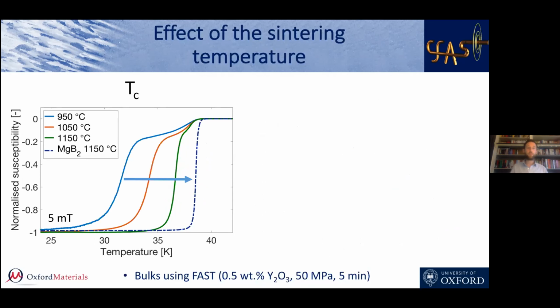Now, another interesting thing was to play with the temperature. So here, we saw that temperature again had a huge effect because after ball milling, the material is heavily damaged. And you can imagine having a lot of dislocations and grain boundaries, and the crystallinity was damaged. And so if you only process it at low temperature, you still have a high concentration of defects, which hinder superconductivity. So your TC is lowered, and can be lowered by almost 10 Kelvin.